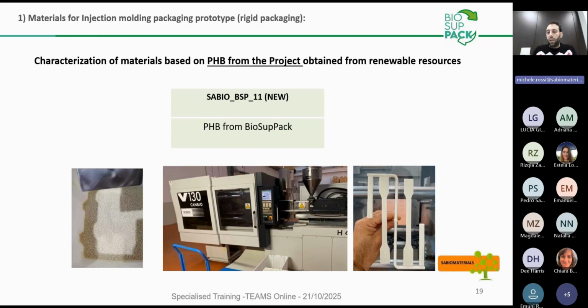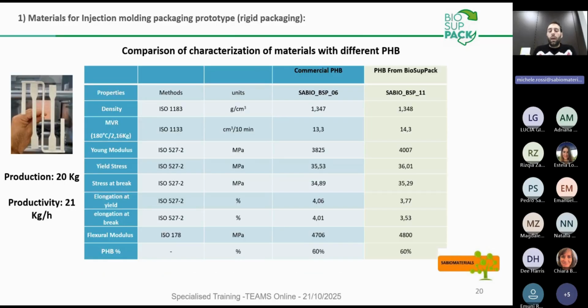Again, the creation of the specimens, the dog bone mold by injection molding, and finally the comparison between the two materials. The material obtained from commercial sources, commercial PHB, and the material, the same material, but only changes the source of the PHB. So for both, the percentage of polyhydroxybutyrate represents the same value, 60%, because it's the same material. The density changes a little bit, only the last digit, but this is not most important in that case. What we would like to be maintained is the fluidity, because at the end we would like to obtain the final article. So the fluidity is a parameter that for us is very important to be kept the same, or at least better, and in this case is